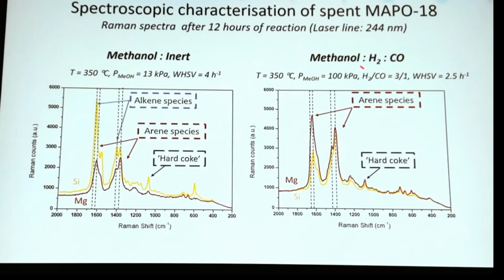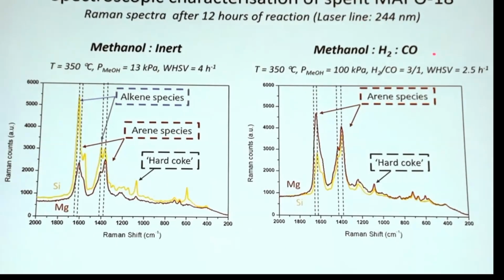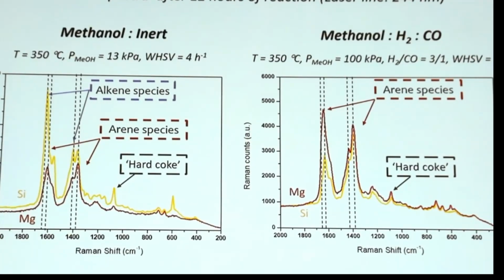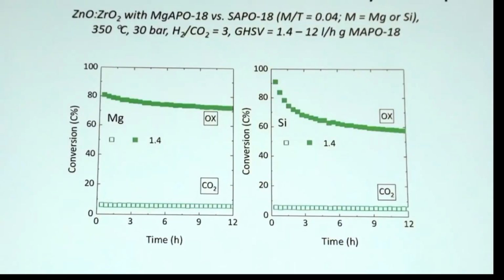If we now co-feed hydrogen and CO, we see that the materials are much more similar. We have now a higher abundance of carbon species in the magnesium material, and we have some hard coke in both materials, and much less of the alkenes also in the silicon. So we see that these co-feed conditions make the materials much more similar.